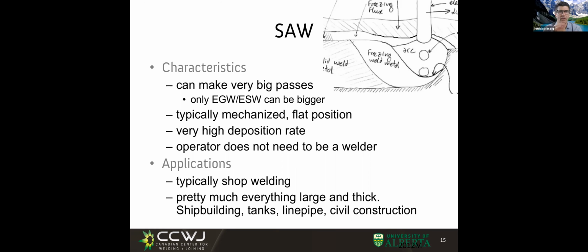There are a couple of reasons why this makes sense. One reason is that it's very difficult to stick a flux to a wall, right? Although there are tricks to hold the fluxes, and people have tried, typically fluxes wouldn't stick. That's one problem. Reason number two why subarc welding runs in position 1, flat, is that subarc welding is meant to have big passes, big productivity. In the flat position, gravity helps you to keep the weld down. But if I wanted to do a subarc weld in the horizontal position, now gravity wants to make my weld sag and fall to the side, right?